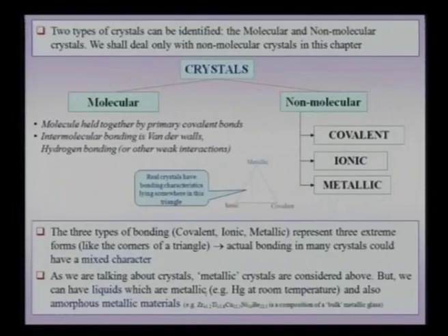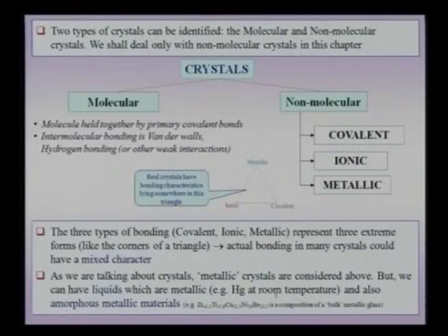For instance, there is a composition containing zirconium, titanium, copper, nickel, beryllium, and this composition can be easily formed into a metallic glass which is known as a bulk metallic glass. In other words, I could attain macroscopic sizes of this metallic glass by slow cooling. Some of these compositions you can cool at the rate of 1 Kelvin per second or slightly more, even 10-20 Kelvin per second, and obtain a glass. That means that if I take a composition like this, melt it and pour it into a copper mold, I can get a glassy material. Of course, I will not make the copper mold too thick, I would like to make it somewhat thin so that the nearby walls can extract the heat, but still these materials can easily be glassified or made into a bulk amorphous alloy.